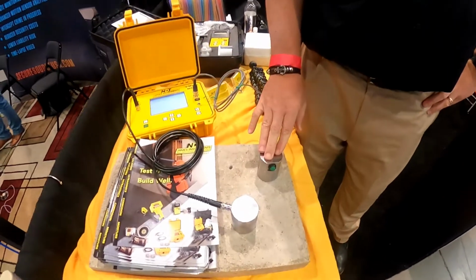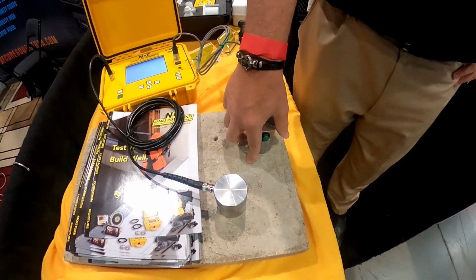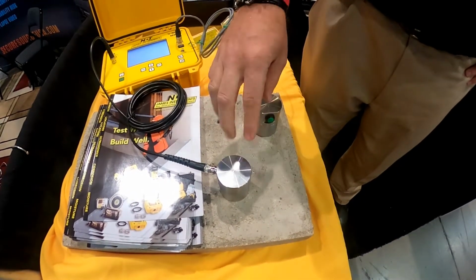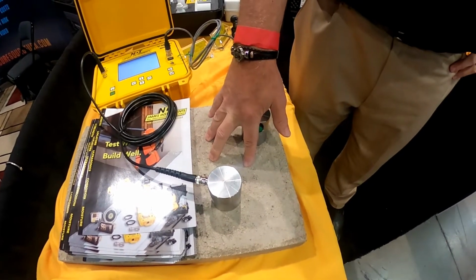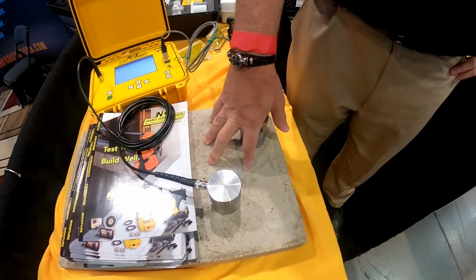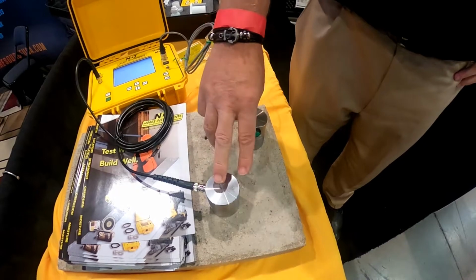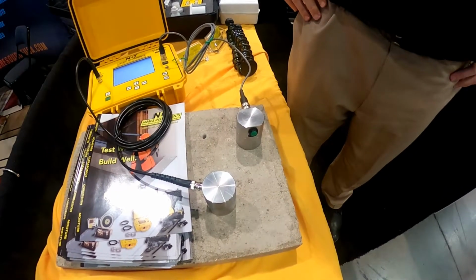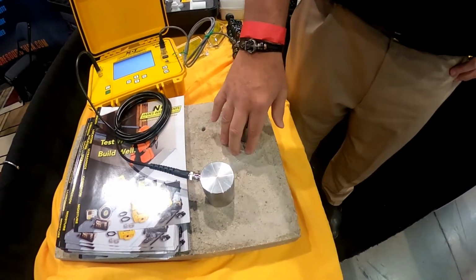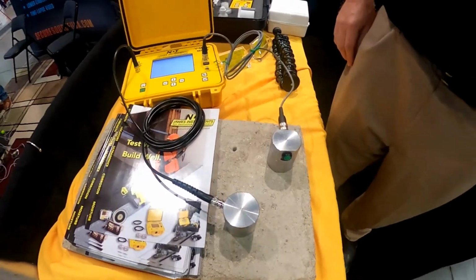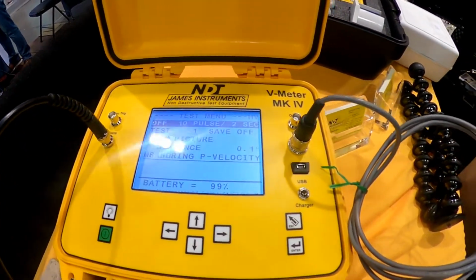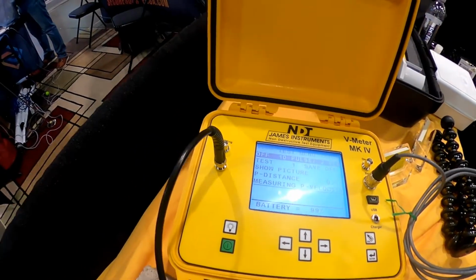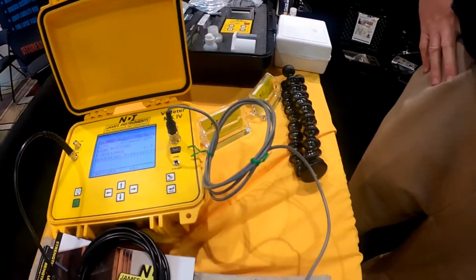We also have here one of our other more popular products, the V-Meter Mark IV. It's the 4th generation. We've had this product going since pretty much the inception of the company. The unit sends a sound wave from one transducer through the material under test to the other transducer. The speed of sound then corresponds to the density of the material. This is a great way to locate cracks, honeycombs, voids, other issues inside the material without having to cut it open. You can also correlate the speed of sound to the compressive strength of the material. And finally, if you have a crack in the material, you can estimate the depth of the crack using the system. All the results can be stored and uploaded later on the PC. And we have a variety of transducers that can be used with the system.